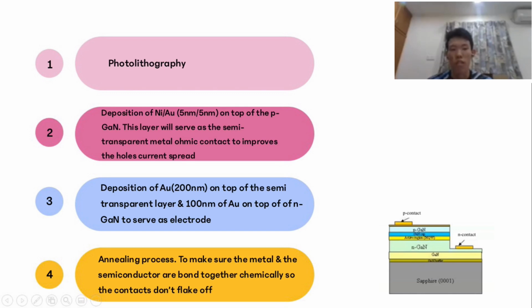On top of the semi-transparent layer, the metal deposited is a gold layer of 200 nanometers, while on top of the N-type gallium nitride, 100 nanometers of gold layer are deposited. After both deposition processes are done, the wafers are then annealed at a high temperature for a long time. This is because it wants to make sure the metal and the semiconductor are bound together chemically, so the contacts don't flake off.